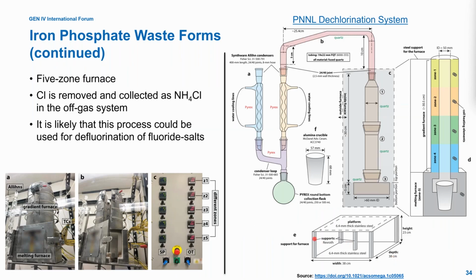To make these iron phosphate waste forms, we use our dechlorination furnace. That's what this is: our 5-zone dechlorination furnace, the Generation 2 furnace. More information down here if you're interested. This furnace is really neat because the front opens, and then the whole thing opens up as a clamshell where I can load my off-gas line, which is represented here in the schematic, into the furnace with the crucible at the same time.